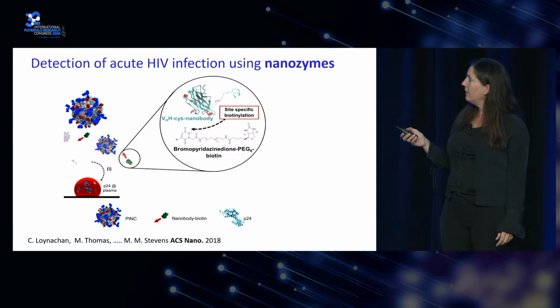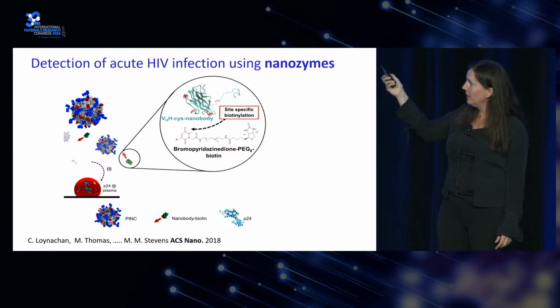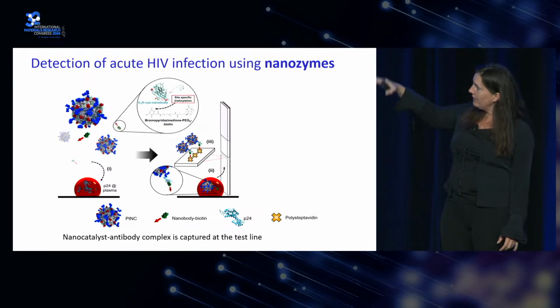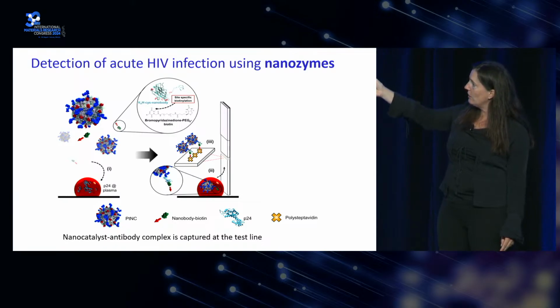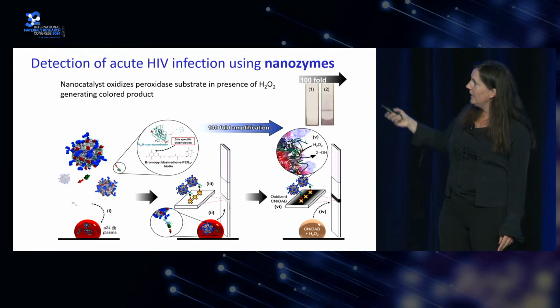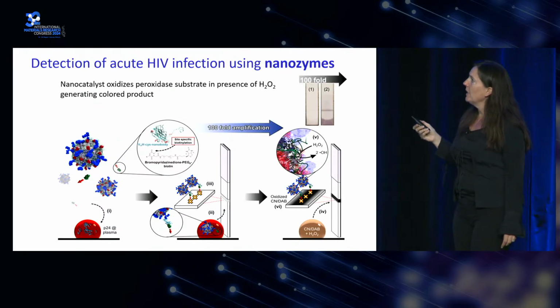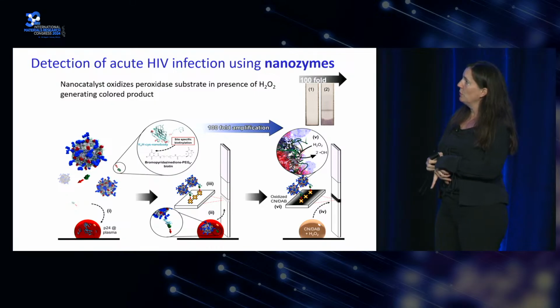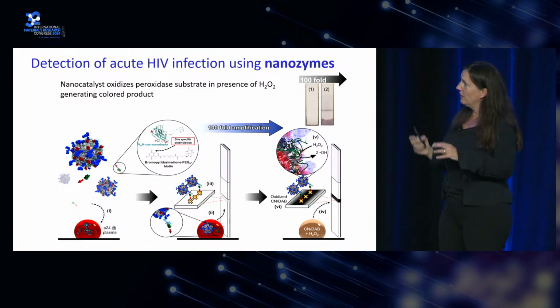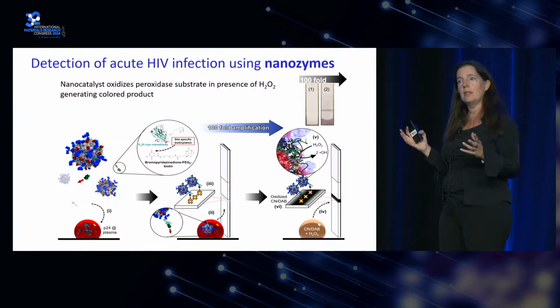And then we have another small nanobody functionalized with biotin, and that can also bind to the target. You can then run these up a test strip. This is like a lateral flow test strip, and the biotin binds very quickly to streptavidin at the test line, and then you can essentially oxidize your substrate into this colored product, and you end up with 100-fold amplification.